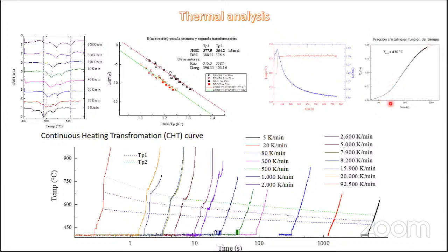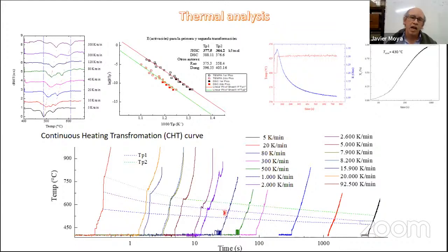Doing isothermal treatment, we can obtain the crystallized fraction. Here we can control the sample temperature up to a heating rate of 1,000 K per minute. That is, we control the heating power in a way that the temperature of the sample runs continually at this rate. For higher rates, the control becomes more difficult.